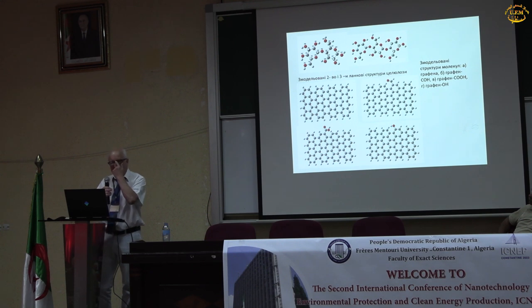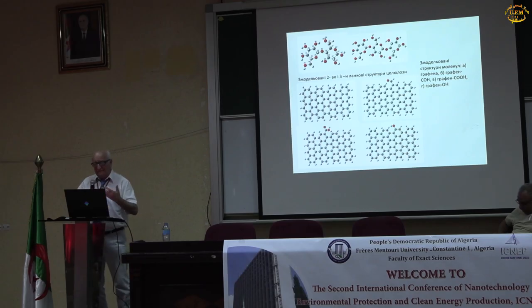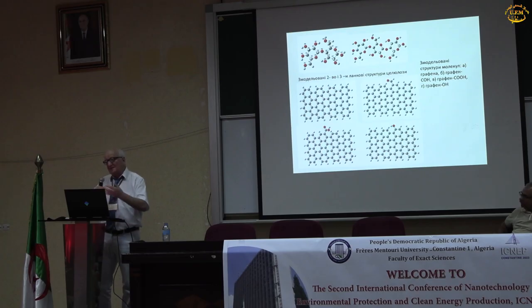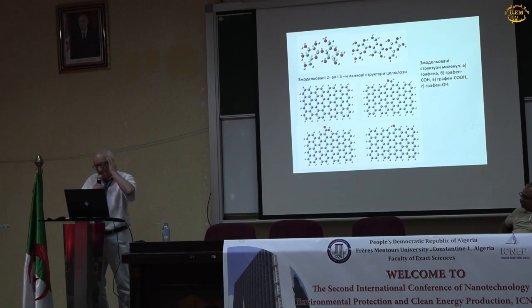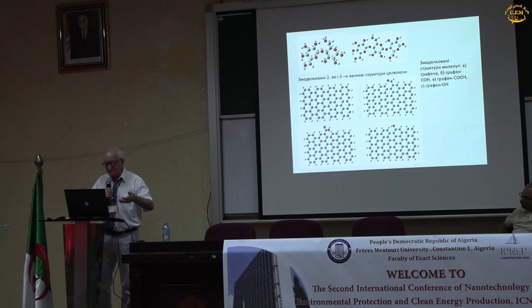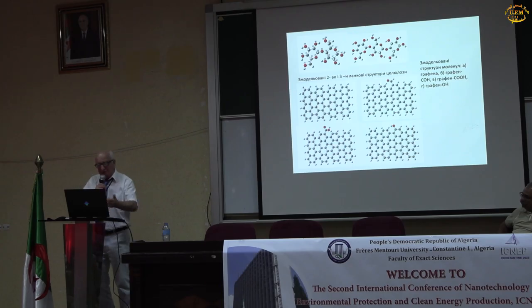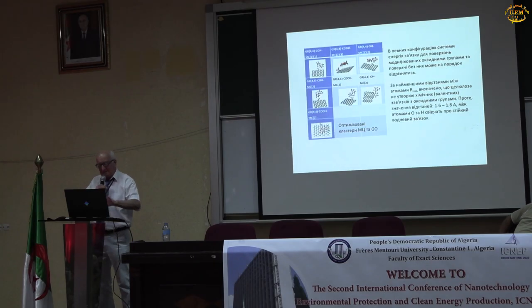The system under study is a very complicated system. So we combine in one research group theoretical calculation, computer simulation, and experimental study. Here I present some of our approaches for computational studies. We use the structure of distinguished cellulose at the top and the modeled structure of cellulose and graphene combined with some molecules, COH and so on. As a result of this computer simulation, we can predict the stable composition and also calculate distances between atoms and the energy of binding between components of the composite.